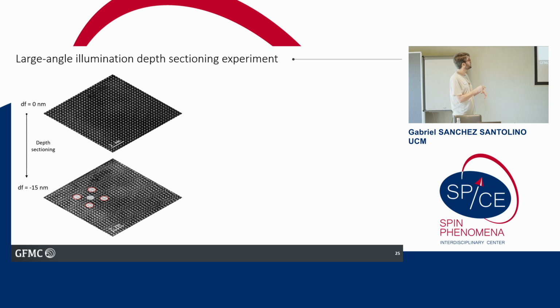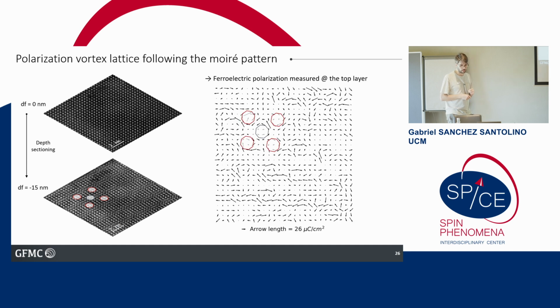So we are going to be doing this depth section experiment. We are going to focus on the top layer, analyze the structure of the top layer, and relate the things we see in the top layer with the position of these AA and AB regions in the Moiré. First, this is a ferroelectric material, and we have this displacement of the titanium atom from the center of the unit cell, and we have this non-centrosymmetric structure. We can measure these electric dipoles for each unit cell, and if we do that, we get this map of small arrows, which just show the shift of the titanium atom from the center of the unit cell, and you start to see how there is some kind of curling of this ferroelectric polarization, right?